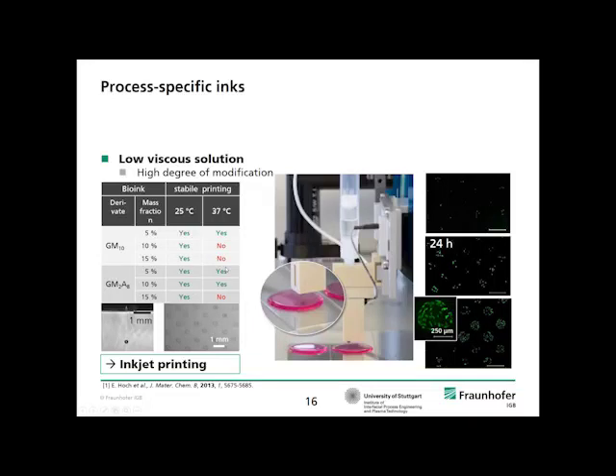We can also formulate inks that are not viscous, like what you saw just on the previous slides, but which are very low viscous, such that they can be used in a drop-on-demand process like inkjet printing. And by this, we can, for example, produce these little pads of hydrogels, which are the small dots here on the hydrogel substrate. And within these dots, we can also cultivate cells.